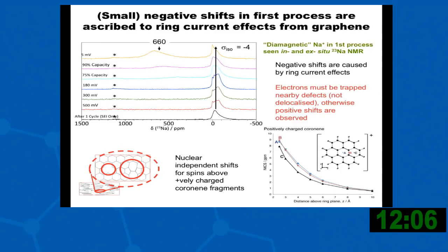We then were able to analyze the beginnings in the sloping region. So this is now showing you enlargements, using a different technique called magic angle spinning, where you can see that in the sloping region we have a peak that's slightly negatively shifted. This is very reminiscent of what I just showed you for the supercapacitors, and it tells you that the sodium is not going into a delocalized metallic environment, and is very much consistent with electrons being trapped near defects and not being delocalized in the graphene sheets.